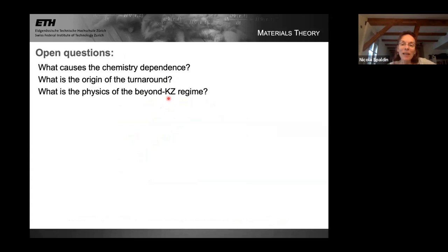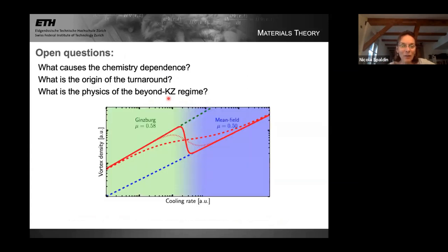We have many ideas. I'll very quickly show you my favorite one. This is a plot of vortex density against cooling rate, this is calculations now, for a fluctuation dominated regime, which is what we've been discussing so far, where the critical exponents are 0.58, the so-called Ginzburg regime, to a mean field behavior where the critical exponents are 0.5. And I would very much like it if the anti-Kibble-Zurek behavior we're seeing is a crossover between these two types of scaling, because I think it would be very elegant, but I have no data to support this. This is just one of the many possibilities.